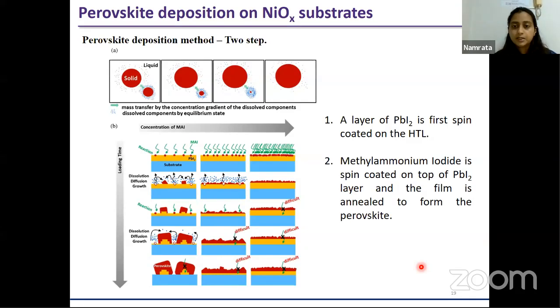So here, in this case, a layer of PbI2 is first spin coated on the hole transporting layer, the nickel oxide, and then methylammonium iodide is added on top of this PbI2. So from the schematic, we can see that first a PbI2 layer is already formed, and then when MAI is deposited, the MAI penetrates into the PbI2, and then we have a bottom layer of PbI2, and on top of that, we have a perovskite, which is formed by the interaction of the PbI2 and methylammonium iodide.